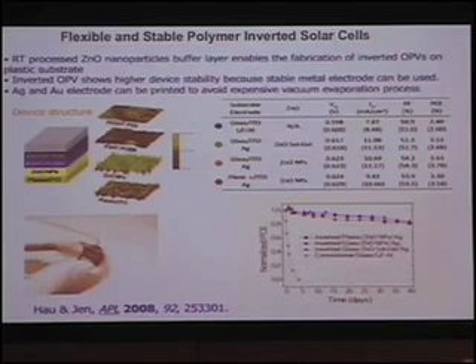And you can see that the device performance is significantly improved because of that. With that said, those were based on the conventional device structures. How about we take this thing and flip it around? Take the zinc oxide coated on the cathode side, and use this to build an inverted structure to collect electrons. With this structure, because it is a room temperature process, we can make flexible solar cell devices very easily and utilize conducting polymer to collect holes on top. Because when you evaporate, for example, silver on top of that, during the evaporation at the interface you have some very thin layer of silver oxide formation. From the energy level, the work function is an exact match of the PEDOT. As a result, you have very efficient hole collection.